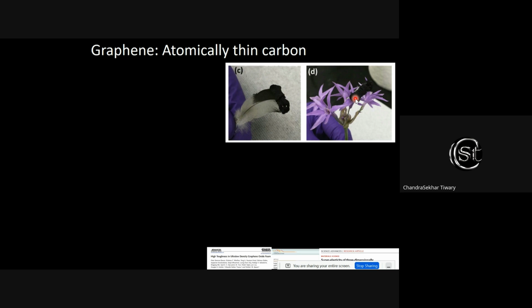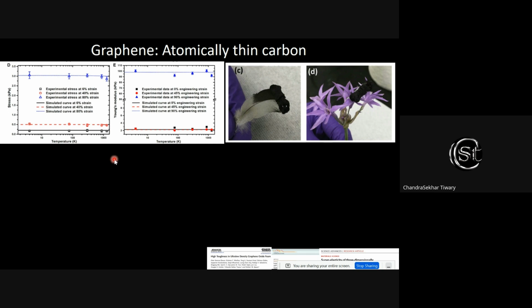Now, what is foam? Foam is mostly blocks with a lot of porosity. Now, these are very different from the plastic or metal foam you use here. The density is way lower than any of the existing foams. It has more than 90% porosity and only 10% or less material. The density is so low that you can literally put them on a feather of a bird or a flower, and they are so light that they can stay there without destroying the base structure. But when you look at the properties, the first time we observed that graphene structures and these foams are one of the only few materials, and so far the only material, which retains its mechanical property all the way from liquid helium temperature, which is a couple of kelvins, to 1100 degrees centigrade.